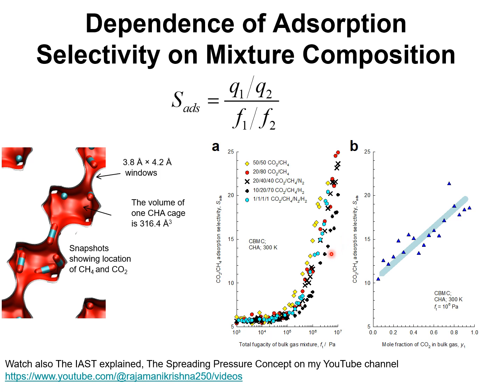The pluses represent the CO2/methane selectivities in a ternary mixture of CO2, methane and hydrogen in the proportion 10-20-70. The cyan colored hexagons are the data on the CO2/methane selectivities in a quaternary mixture of CO2, methane, nitrogen and hydrogen in the proportion 1-1-1-1-1. We note that at any given total fugacity of the bulk gas phase, Ft, the selectivity depends on the mixture composition.